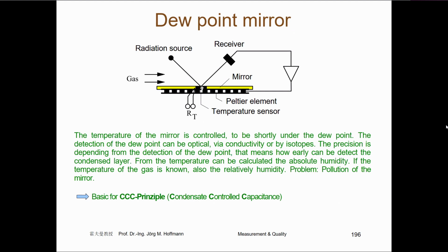But the tubes are going, for example, through the Baltic Sea. They are going on land. So you have different environmental temperatures. And then every time the question is, how much do I have to dry the gas so that you get no water inside of the tubes, because over time that would destroy the tubes by rust. And so you have to dry this gas at first. But the drying process needs a lot of energy, and therefore it should be dried only as much as necessary.